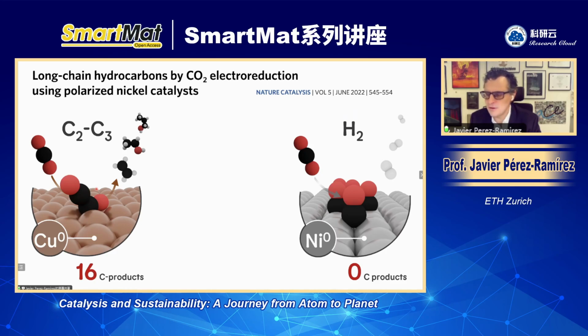Copper is the most extensively studied electrocatalyst because it's claimed to be the one that produces more multi-carbon products. Up to 16 carbon products are produced, right? And we decided to look into nickel. But not just metallic nickel, right? Because metallic nickel is actually a pretty terrible catalyst for CO2 reduction.